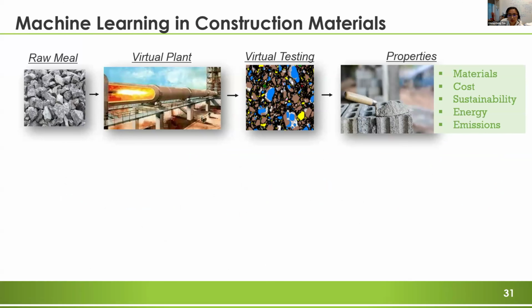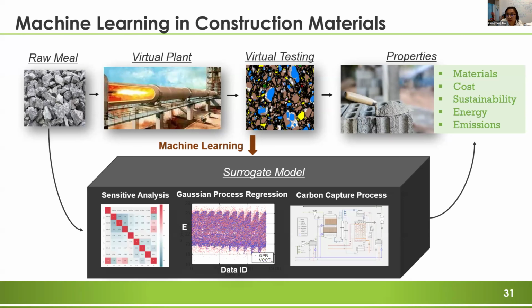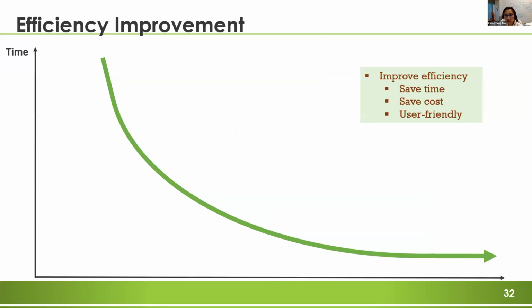So in order to further improve the computational efficiency for the modeling and optimization, I applied machine learning techniques to improve the simulation process. I developed a surrogate model for the whole process, from the raw material, cement clinker production, cement hydration, all the way to the final products. For example, I applied the Gaussian process regression algorithm to train and test the dataset from the integrated VCP and VCCTL models, and the surrogate model works quite well with the larger dataset. So the AI-based optimization and machine learning techniques significantly increase the efficiency for the cement industry.